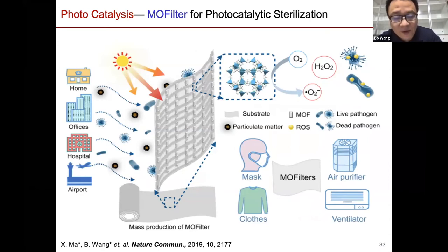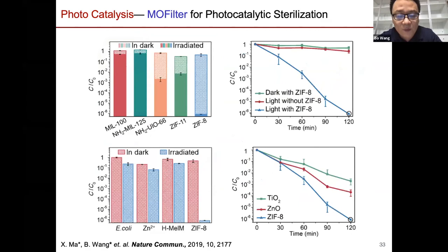In the last part, I want to briefly mention one of the recent works we did using those MOF membranes or MOF filters for further biocidal purposes. In this case, we want to kill some of the bacteria. Now, some of the MOFs under sunlight can generate different types of radicals. In this case, we tested all of them for the process to kill E. coli. We realized ZIF-8 by itself is surprisingly good for such a purpose.